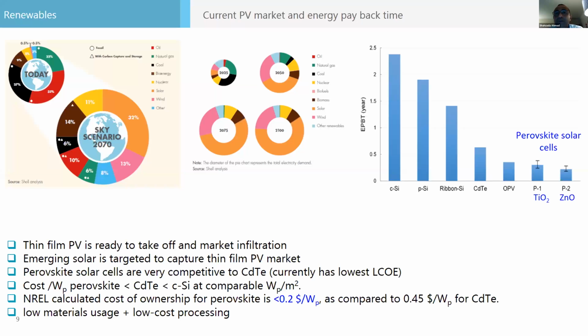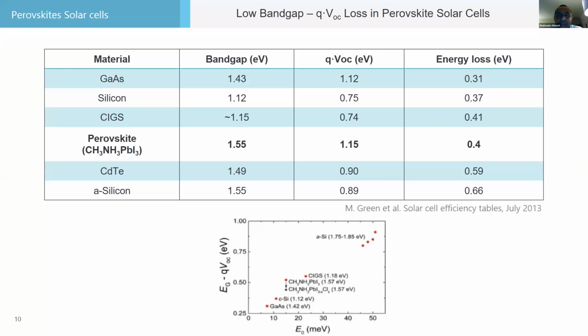Some of the companies are working on making a tandem of silicon with perovskite, CIGS with perovskite. On the other hand, silicon and CIGS are very stable products, and for perovskite, we are trying to reach those numbers to be stable. If we go into the electrical properties, the losses, why these solar cells work well: the losses in perovskite solar cells are at par with gallium arsenide or silicon solar cells. There are very few losses, because the thickness is less, so the charge is extracted and travels to the electrode before dying. Gallium arsenide, silicon, CIGS, and perovskite has even lower.